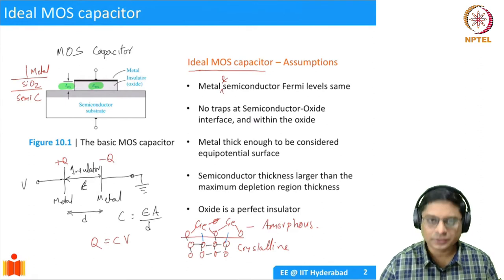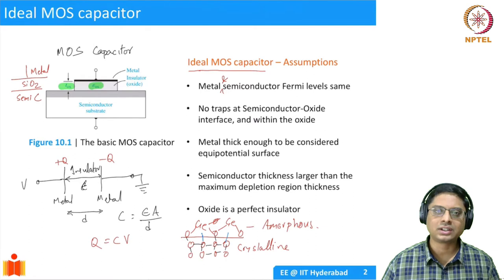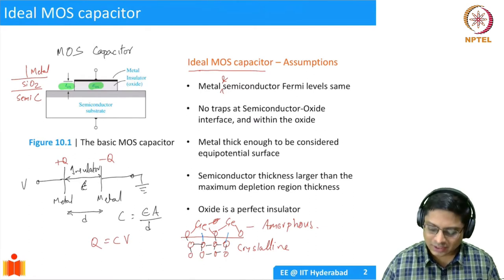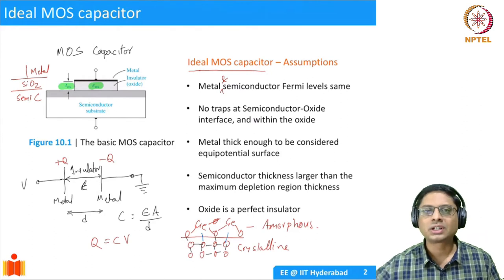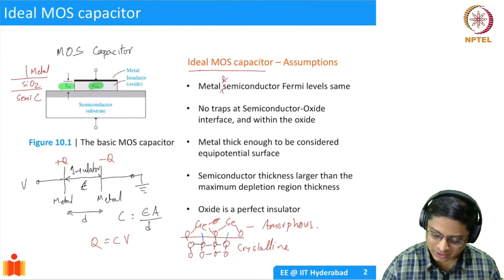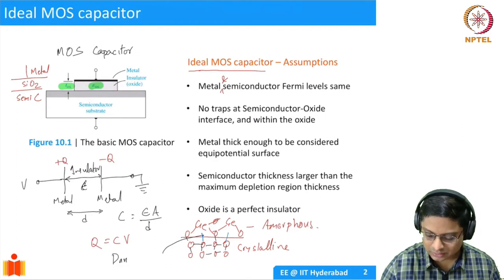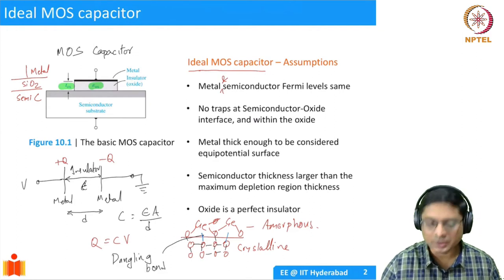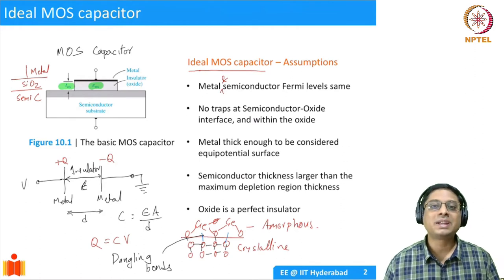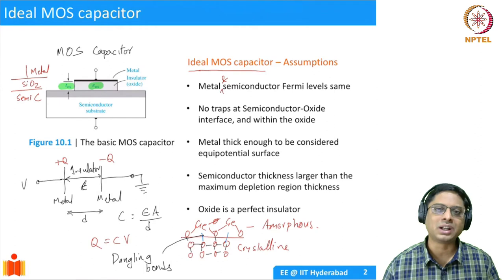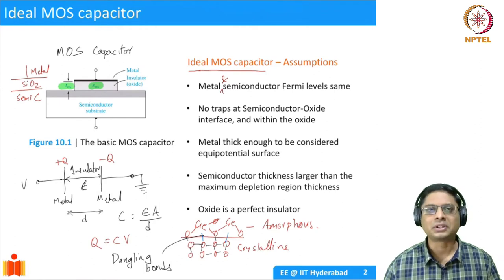But now it turns out that if you form this interface between a crystalline and an amorphous material, there are some atoms of germanium which are not connected to any atom of oxygen or germanium. So these we call dangling bonds, just to indicate that they are not connected to any atom. They behave like a trap, and they actually deteriorate the electrical properties of the device. So it turned out that even though germanium was one of the first semiconductors to be investigated, the interface between germanium and germanium oxide was not very good. Whereas the interface between silicon and silicon dioxide was extremely good. It has a very, very low defect density. We will talk about that later.